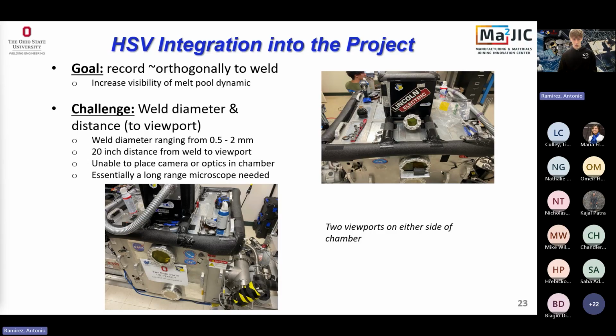But like I said, there's a lot of challenges recording this. So first of all, the weld diameter is tiny, tiny, tiny. Laser welds with the spot size that we use range from maybe 0.5 millimeter to 2 millimeters. And in combination with the other issue, which is the 20-inch distance from weld to the viewport, which we use to look into it, creates a condition where we basically have to have a long range microscope to see really what's going on. So I will explain that in a little bit, but you're unable to place the camera or any optics into the chamber at all, just because the high vacuum will mess with how the camera works and will cause it to overheat and things like that.